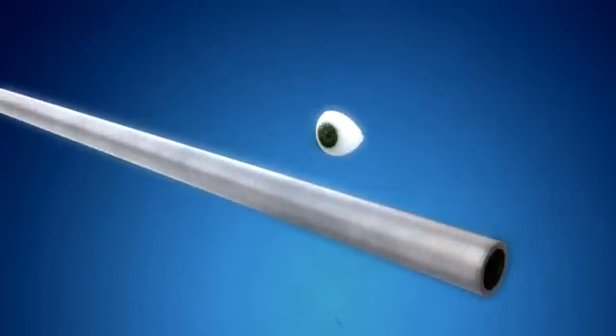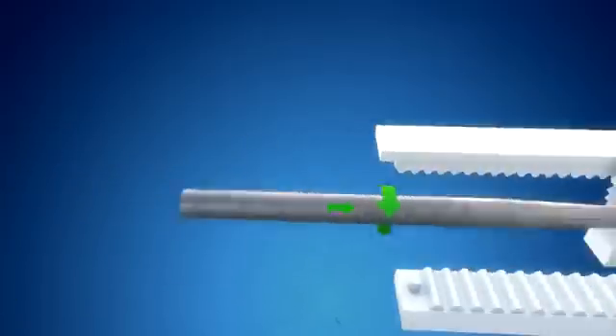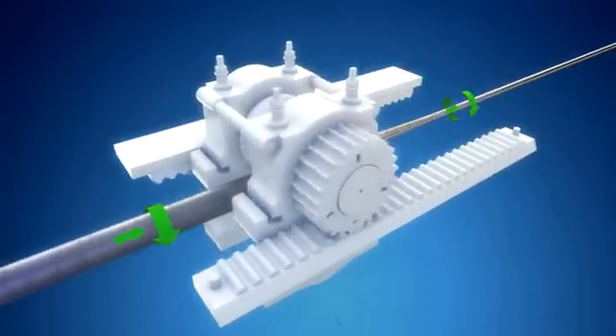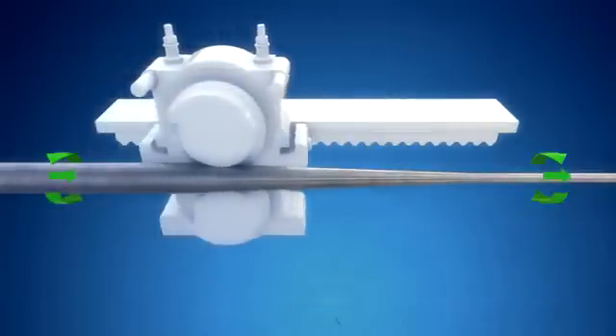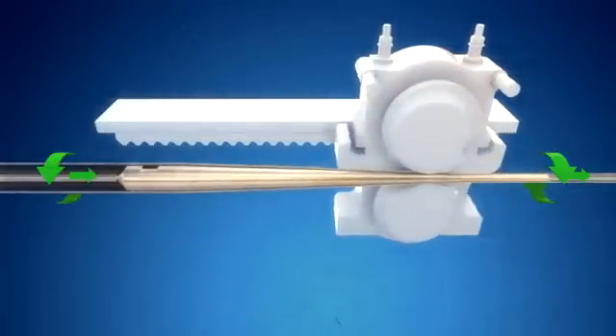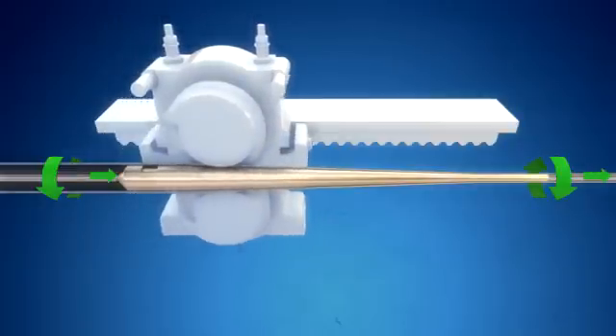Following visual inspection and X-ray spectrometry, the tubes pass through the pilger mill where they are cold rolled to requested dimensions. The inner diameter is determined by the tapered mandrel.